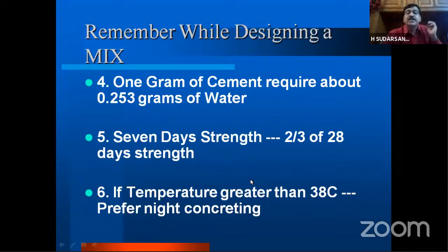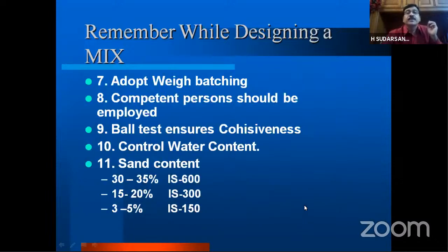If the temperature in the environment is more than 38 degrees centigrade, prefer night concreting. Always adopt weigh batching, don't go for volume batching. Skilled persons should be used in the mix designing and mixing. You can ensure the cohesiveness of the concrete with the ball test and control the water content. As you know, water is dangerous for the concrete. The proposed sand contents for the different grades, IS 600, IS 300, IS 150 microns: 30 to 35% of 600, 15 to 20% of 300, and 3 to 5% of IS 150.